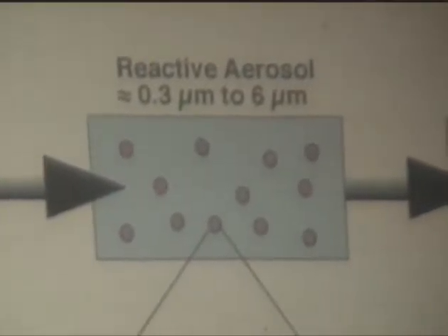So this more or less shows that kind of business. And one system for making silica would be to do this with TEOS and water. Ethanol is a byproduct. There's no solvent to mix water and TEOS because you're just condensing vapors together. And HCl is a gas that's present as a catalyst in this.